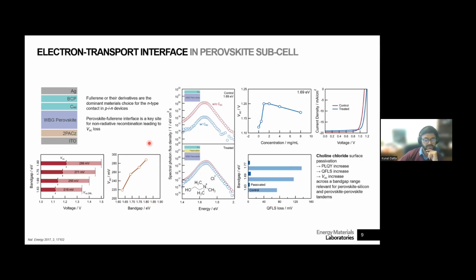And what we tried to do is we looked at this interface specifically. So the interface between the perovskite and the C60 layer. And when you conduct an absolute photoluminescence spectroscopy experiment, that basically translates to your PL quantum yield, which translates to your quasi-Fermi level splitting, which translates to your voltage. You can see that if you take the bare perovskite, so just the perovskite by itself on glass, you get a spectrum which looks like this. And the moment you evaporate a C60 layer on top of it, your emission intensity drops, and therefore the quantum yield also drops, right? And that yield implicitly means that the quasi-Fermi level splitting has also dropped.